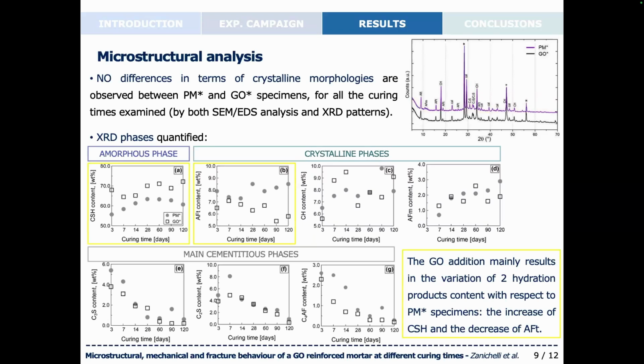Then the AFt content increases for the PM* specimens, whereas a completely different trend is observed for the GO* specimens, where it decreases. For the other crystalline phases, as well as for the main cementitious phases, no significant remarks can be made. So at least for the microstructural analysis, we can conclude that the GO addition mainly results in the variation of two hydration products content, that is the increase of the amorphous phase and the decrease of the ettringite.